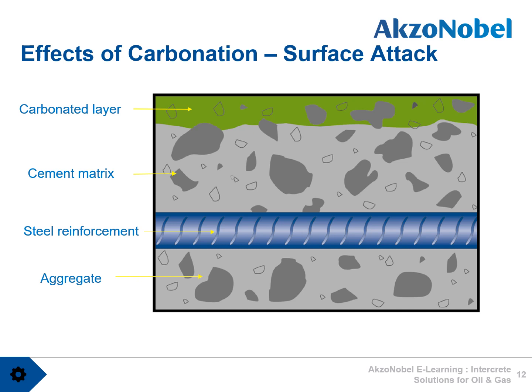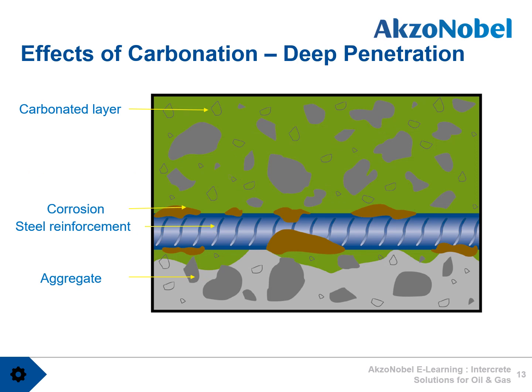You can see the green area is the carbonated layer. The steel is still protected by the concrete. And sometime later, the carbonated layer has reached the depth at which reinforcing steel can be found. And obviously, if there is less concrete cover, this will happen sooner. The thickness of concrete cover is critical, and this is something we'll return to later. The ingress contains everything required to corrode steel, and that's exactly what begins to happen. Because corroded steel occupies a larger volume, it needs to expand, and this is when the forces of expansion can force the concrete to fail and break away.